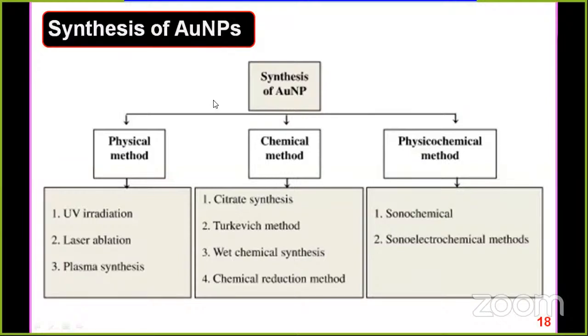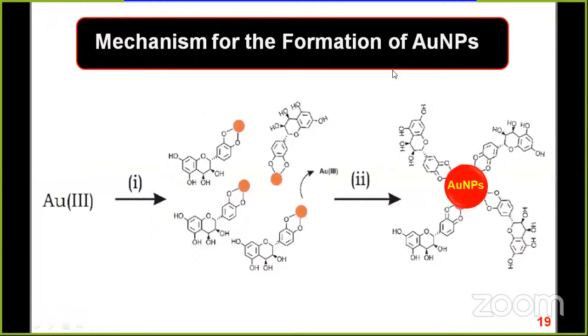Oxidation state 0. See how it is formed. So we have taken gold chloride, and this is the ligand, so it is attached. Then we added the reducing agent, and Au3 becomes Au0. Because of this reducing agent, it gets reduced and binds on the surface. So this end is free from the binding, and this end is attached on the surface. The free-ended part stabilizes the nanoparticles.